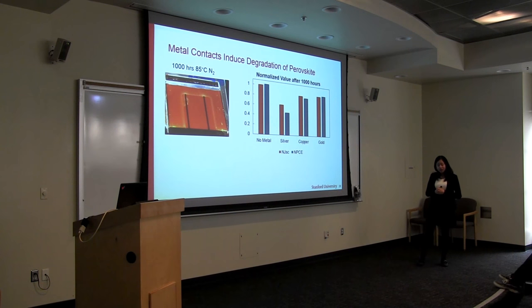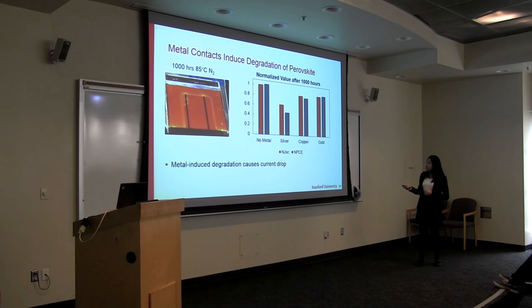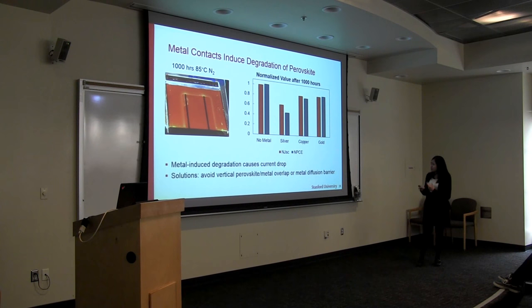And when I tried to figure out whether this effect is true for all metals or just silver, I did an experiment comparing a solar cell without metal and solar cells with silver, copper, and gold as electrodes separately. We see that the ones with metal have a very severe drop in current, which also caused a drop in performance, while the one without metal did not have any drop.